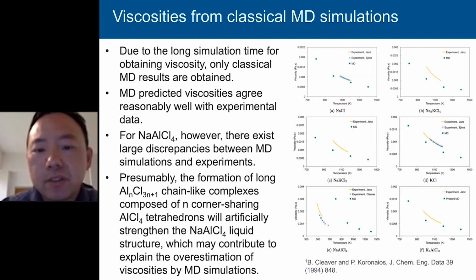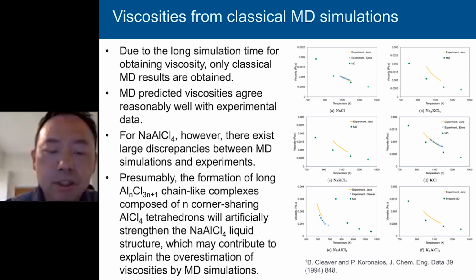So, if you look at the right figure, where I plot the classical MD predicted viscosities, which are shown as the green circles, and put them against the experiments, I would say the agreements are pretty reasonable for almost all the salt compositions, except one, which is the sodium aluminum chloride 4 composition. For this composition, there are some large discrepancies between MD simulation and experiments.